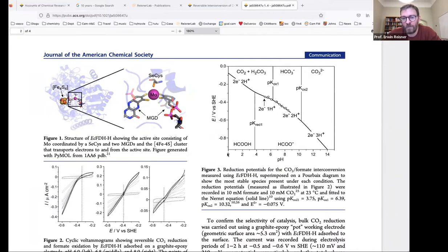Because if you go from pH 0 to 7, for example, you do not form the same product. You only form formic acid under very acidic conditions. And when you go to neutral pH, you're actually forming formate. So this means that it's a two electron one proton couple. And this shifts. It's not a linear line. And those are the pKa's, all of them. It's quite complicated, actually. But the correct potential is that you're very close to proton reduction at pH 7.